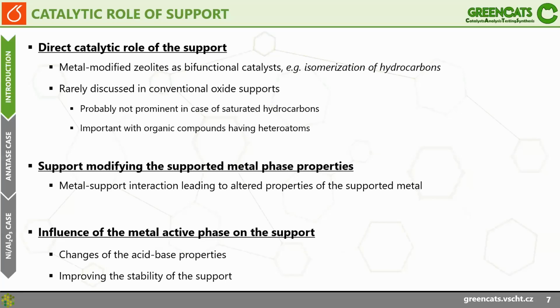And one can see that when people discuss, for example, the stability of metals supported on alumina, where adding the metals helps to stabilize alumina against the action of water, because alumina as such is quite susceptible to the effect of water in the reaction mixture. And again, this is something that is going to happen to us when we work with biomass-derived feedstock. So then they can even improve the stability of the support.